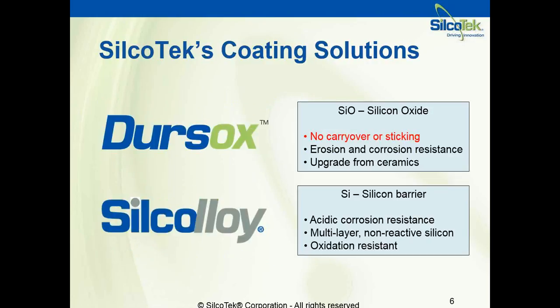We have two coatings that are focused towards the semiconductor industry. The first is a new one for us. It is called Dursox, and it is a silicon oxide variation of our Dursan coating. So the major points to take away from this one is that it prevents carryover and sticking with a very low surface energy. So in the same right, it also resists erosion and corrosion very well and can be considered an upgrade for ceramics, as it is very semi-ceramic in nature as an SiO.